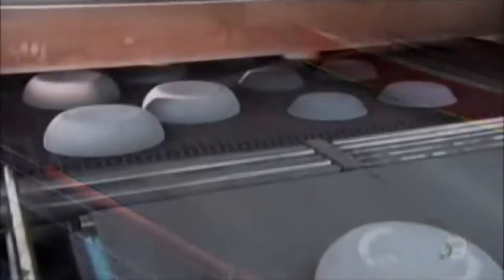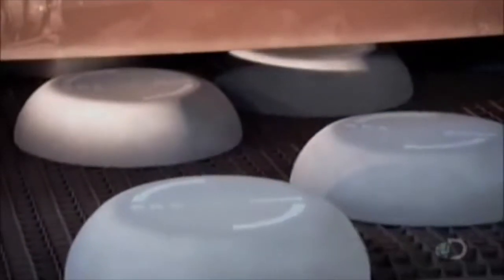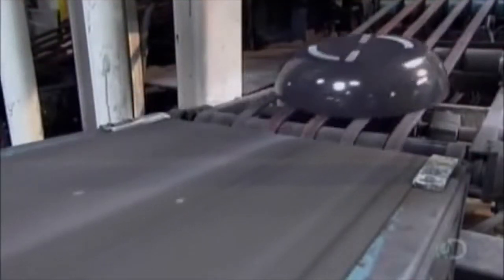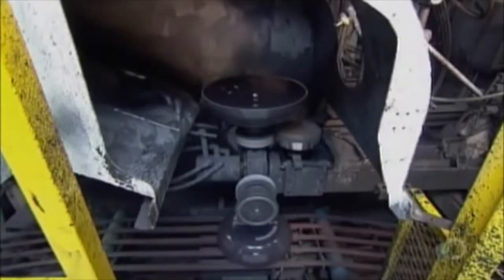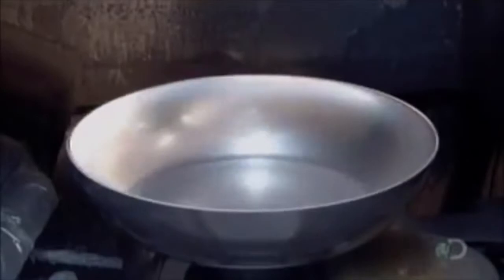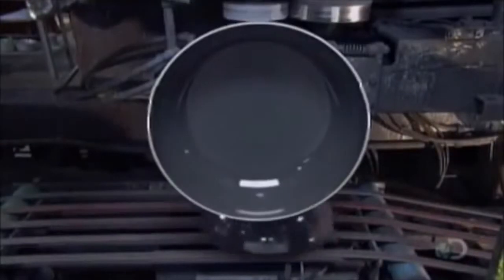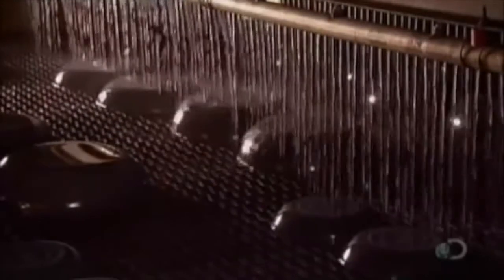The pans enter a long curing oven heated to 560 degrees Celsius. The cure toughens the enamel and adds gloss. For the inside coating, a suctioning device picks up the pan and turns it around. A sprayer applies a special primer followed by a non-stick coating, and the pans receive two layers of this non-stick substance. The pans journey through the oven again to cure the non-stick finish at around 425 degrees Celsius. On exit, water rains down to rinse off contaminants, and lastly they go through an infrared light chamber to dry off.